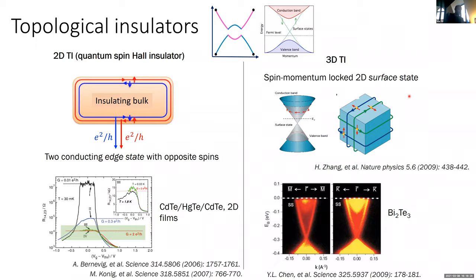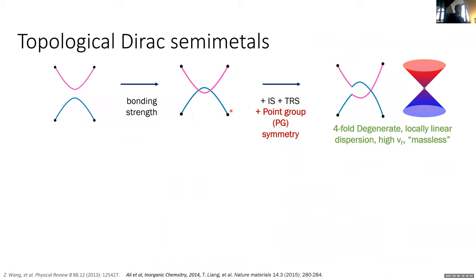Dirac semimetals are very related, of course. Again, you have essentially band touching or inversion, but this time with the addition of a point group symmetry, like a fourfold rotation, for example, or a sixfold rotation, you can end up demanding one of these degeneracies. And that results in a fourfold degenerate, locally linear dispersion. Basically, and that's important, you can get very high Fermi velocities.